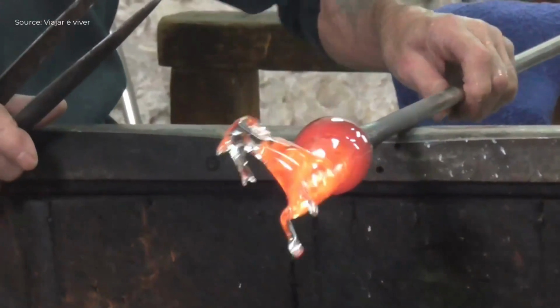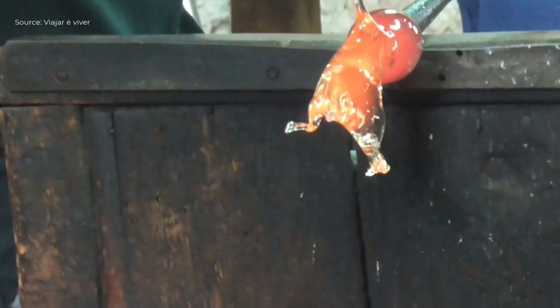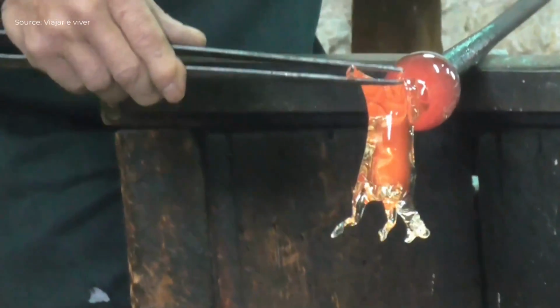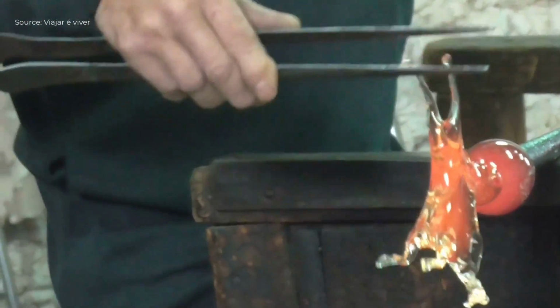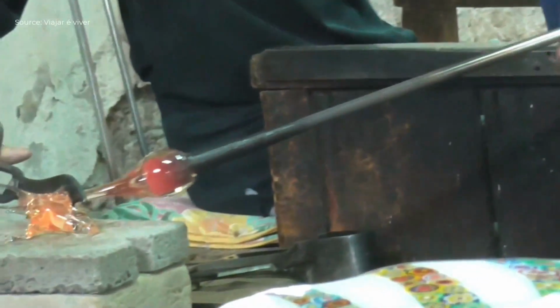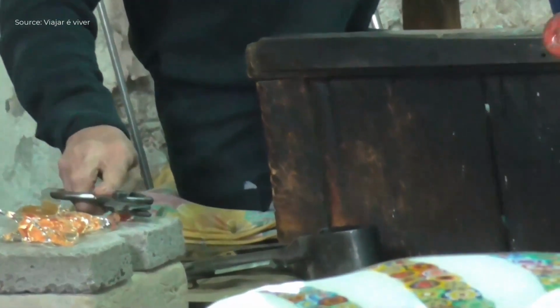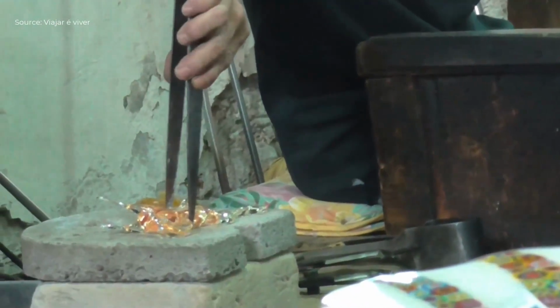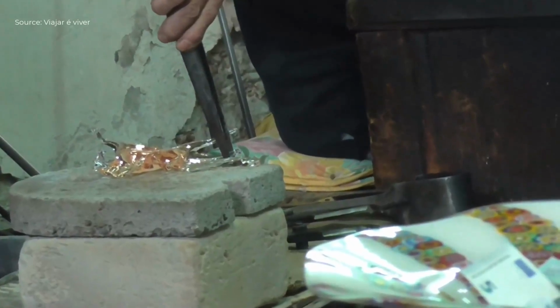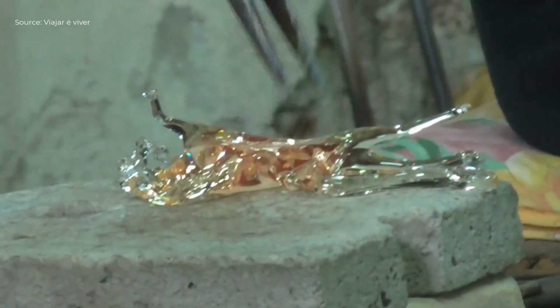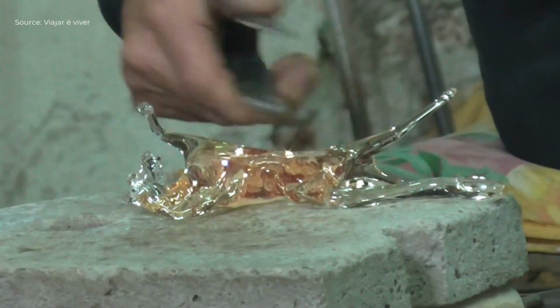Once the sculpture is completed, it is placed into a special oven at around 700 degrees Celsius. This annealing process is essential to gradually reduce internal stresses in the glass. The horse remains in the annealing oven for 24 hours to prevent thermal shock, which could otherwise cause it to explode once cooled.